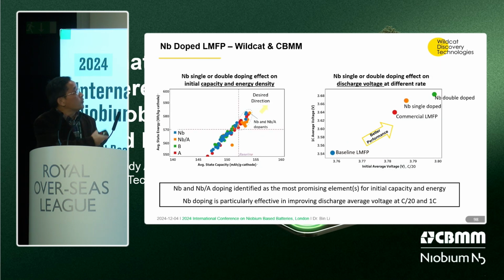So this further demonstrates the niobium doping study. Here also is cycle 1 capacity and also energy density, because what matters is energy density. You can see all of those niobium, or niobium with double doping with element A, show the best performance in terms of both capacity and energy density. And actually, the energy density you can see here is higher because you have average higher voltage. It's showing the baseline when we started this project with the CBMM.